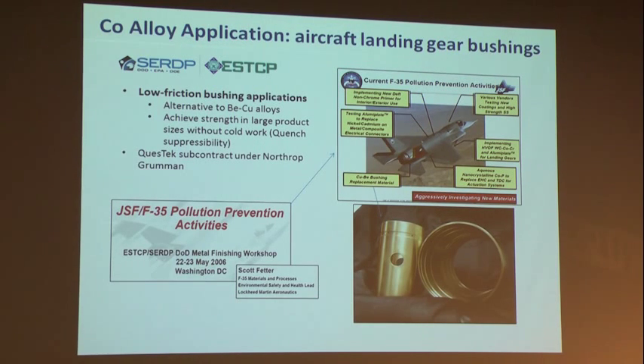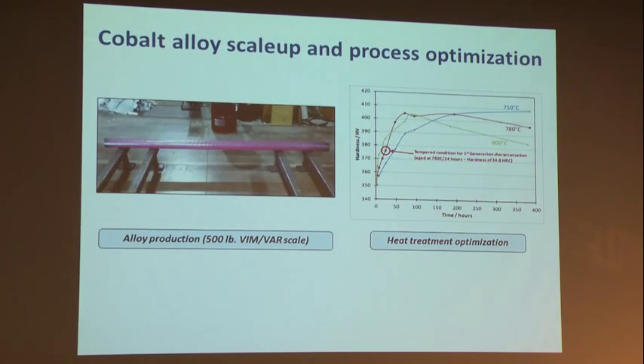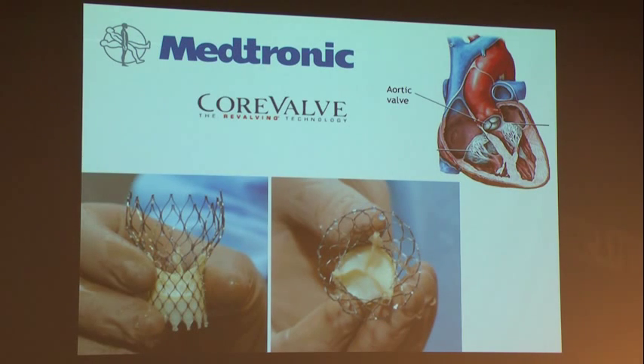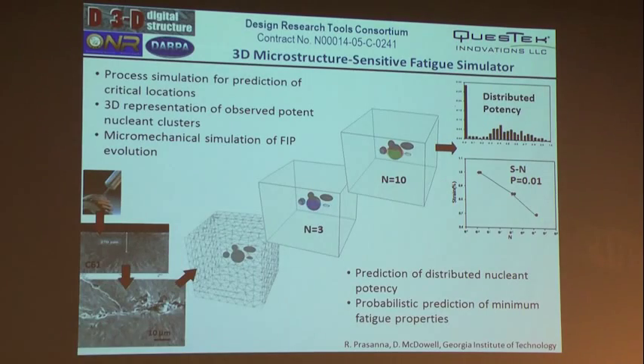In the use cases, we have a large activity in precipitation hardened cobalt alloys, and one of the places where, in addition to going after very high performance cobalt alloys for aeroturbine applications, QuesTek has already designed for low temperature alloys a new bushing alloy to replace beryllium copper. And this is the area where we're applying the AIM methodology and demonstrating and improving that methodology to accelerate the process optimization of this new cobalt alloy. We're doing very similar things for medical applications in designing higher fatigue performance shape memory alloys that can enable these kinds of medical devices.